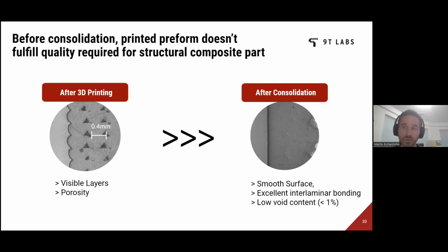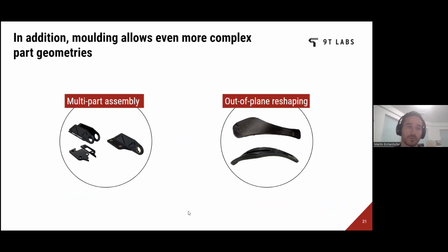So after consolidation, it's a real molding process above Tg, not just above Tg, also usually close to melt temperature or above melt temperature. So we're really remelting the part, co-consolidating the part all together. So there is perfect surface finish, what you would know from injection molding or molding in general. You would have perfect interlaminar bonding, and you have very low residual void content in the part, which we're usually shooting for below 1% void content. So that's a quality aspect, very important for getting into serious production and real metal substitution.